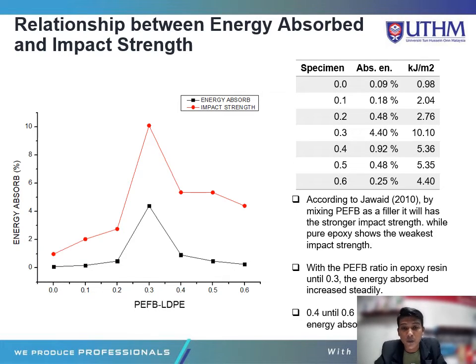According to Jawaid 2010, mixing PEFB as a filler gives stronger impact strength, while the pure epoxy shows the weakest impact strength. With the PEFB ratio in the epoxy resin up to 0.3, the energy absorbed increased steadily. Ratios 0.4 until 0.6 show a decreasing energy absorbed trend.